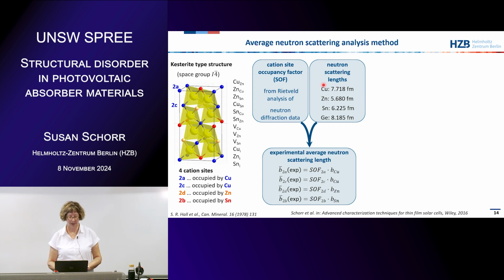So now we have the neutron scattering length, which is tabulated, for example, for these 4 different elements. And this is our site occupancy factor we get from the refinement. And we use this site occupancy factor and multiply this with the neutron scattering length of the atom which should be on that site. So with the neutron scattering length of copper for the 2A site, we get what we call the experimental average neutron scattering length, because this site occupancy factor determines the real scattering power of the site.